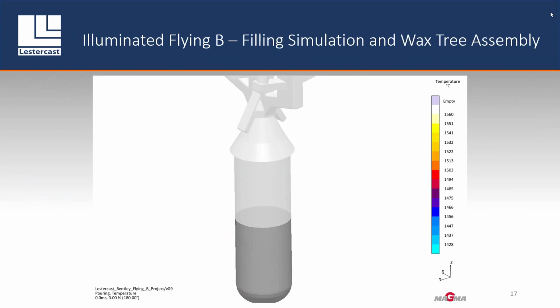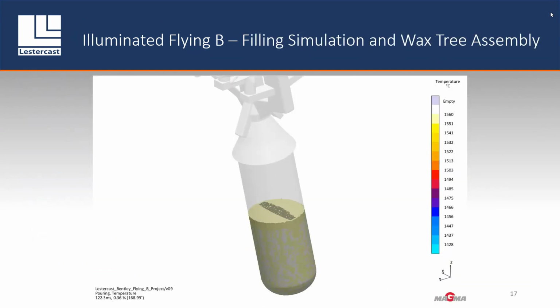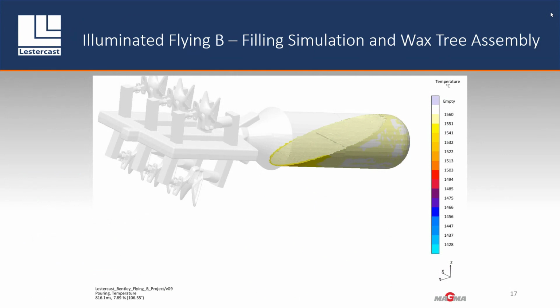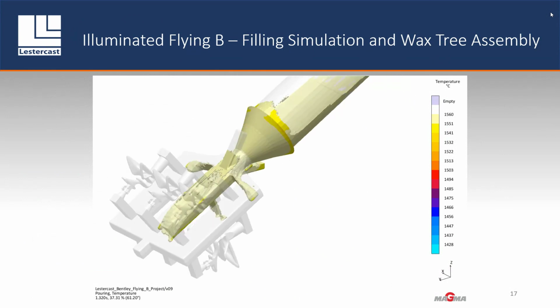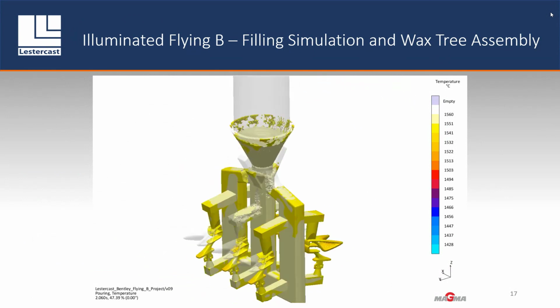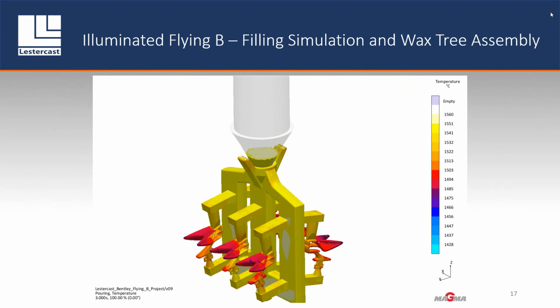So what you can see in this movie here is it's going to play for me. There we go. We can see the metal cascading down into the tree, and then obviously into the individual parts down here. And we're looking at a temperature scale here. So this looks from the pouring temperature, which is set at 1560 C, down to the liquidus of this particular 316 alloy at 1428. So we knew that from a filling point of view, we were getting nice hot metal